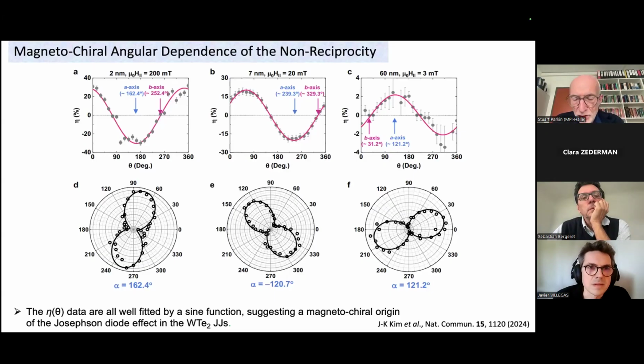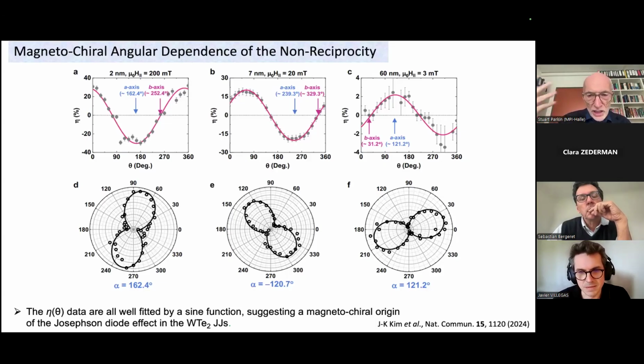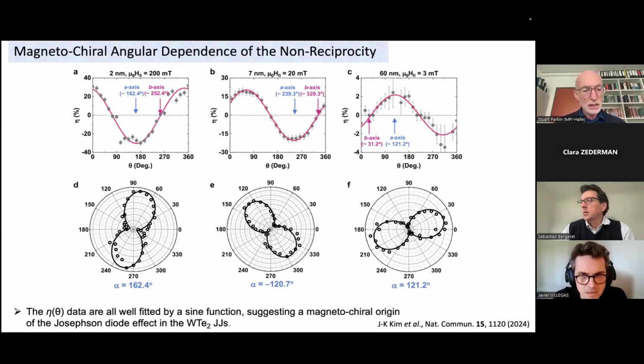And this gives rise to an extrinsic diode effect. And so some groups have claimed, oh, all these effects are extrinsic. But we believe in our cases, we see an intrinsic effect. On the one hand, we believe that because we can account for the complex temperature and field dependence of the diode effect with a finite momentum Cooper pairing model. And on the other hand, in this case of tungsten ditelluride, because of its low orthorhombic symmetry, we can demonstrate that the Josephson diode effect is connected to the crystal structure itself.